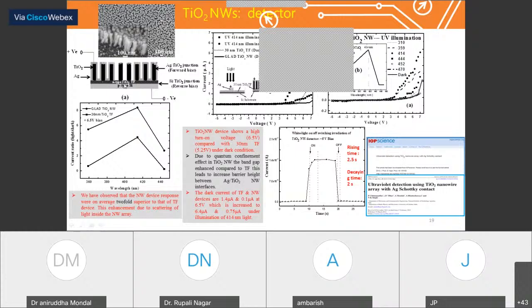This is the cross-sectional schematic diagram of the device. We have taken the P-type silicon, then an N-type titanium dioxide thin film, on which a nanowire-based anti-reflection coating of titanium dioxide has been used, as an anti-reflection coating as well as the active region of the device. We use silver as the upper electrode and indium as the lower electrode of this kind of device.